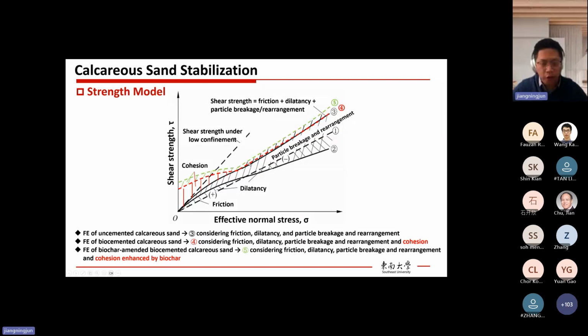And at high normal stress level, although the cementation has been destroyed, the existence of biochar in soil structure, as I mentioned, could change the soil surface morphology, could improve the density. So it could still be a little bit higher than the original failure envelope. So this is the stress model we proposed for both the MICP treated case as well as the biochar enhancement case.